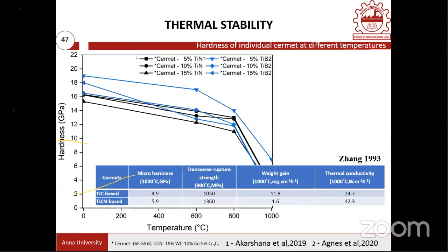Therefore, if you look at this curve, and this Zhang et al. Zhang in the year 1993, he has come out with the value for this thermal stability. TiCN based material has the micro hardness value 5.9 gigapascal after heating to 1000 degrees centigrade. So this is the value, but earlier without heating it might be 12 GPa, but after heating to 1000 degrees centigrade, the TiCN based CERMETS show only 5.9 GPa hardness value. TiC based CERMETS are offering only 4.9 value.